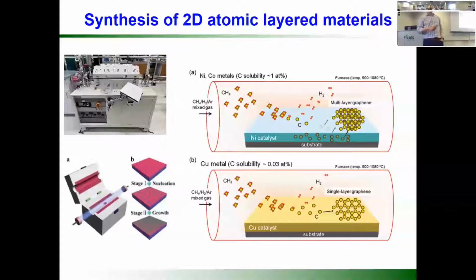And here's how we fabricate the graphene material. In our lab, we use the CVD technique. CVD, chemical vapor deposition, uses the gas methane. Methane is CH4, so we decompose it to get carbon at a very high temperature, 1,000 degrees Celsius. But it takes about 3 to 4 hours. We get about a 5 by 5 centimeter scale, and then we transfer it to the substrate and fabricate the device. It takes a lot of effort to make the sensor.